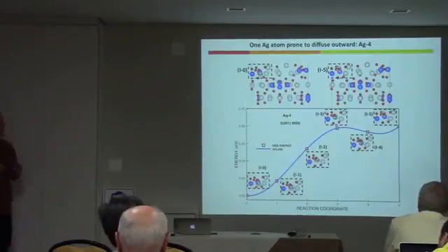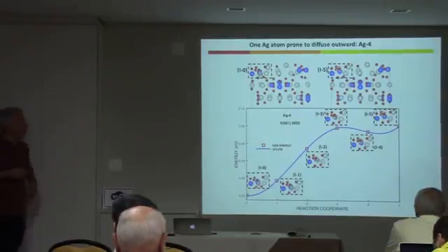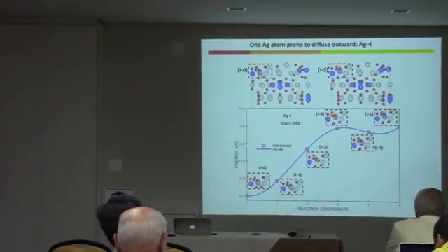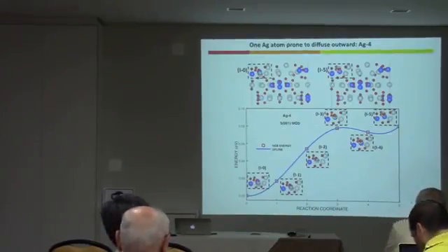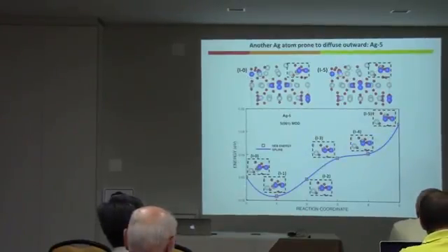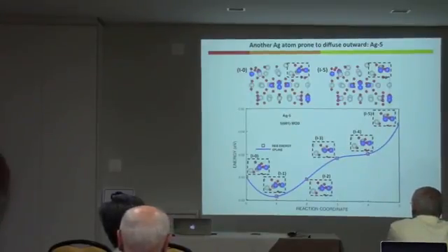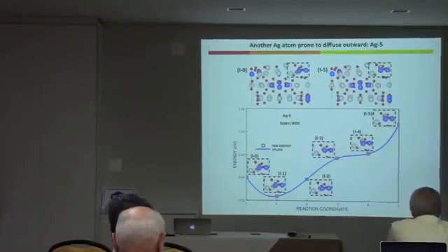And we found again some atoms that can diffuse easily and others that remained in the bulk positions. And we found that the energy barrier is very low too, lower than 0.06 electron volt, which is quite low. And we find this minimum again.